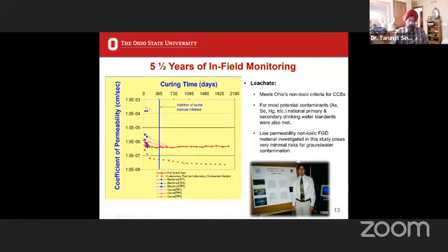Here is what I want to show you. This is the solid line. I'm showing the coefficient of permeability in centimeters per second. You can see that in the first year, the permeability was anywhere from 10 to the minus 6 to 10 to the minus 7 centimeters per second, and then it stabilized. Even after the addition of swine manure, no significant changes happened.